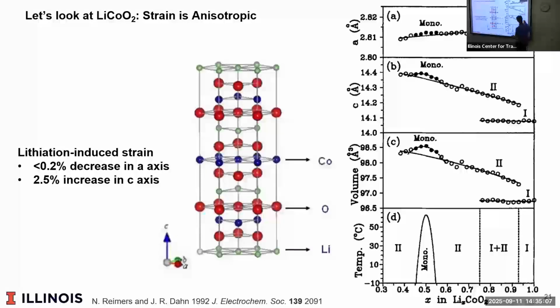But as this is swelling and contracting, here it actually undergoes a phase transition. You don't want to go into here because things crack, because it's actually changing crystal structure. But if you stay in some of these intermediate regions, you don't put as much mechanical stress on the inside of your battery, which can lead to cracking. This is not true for all battery chemistries, I should say.